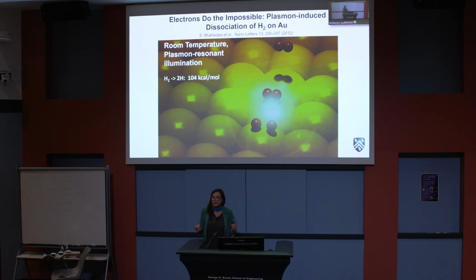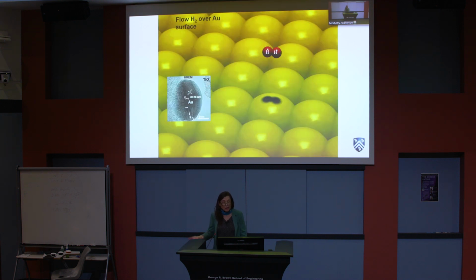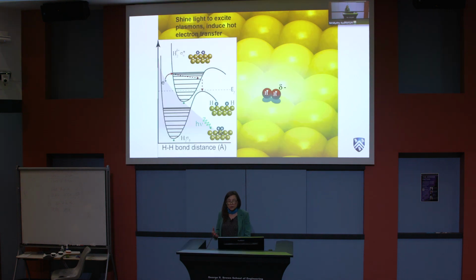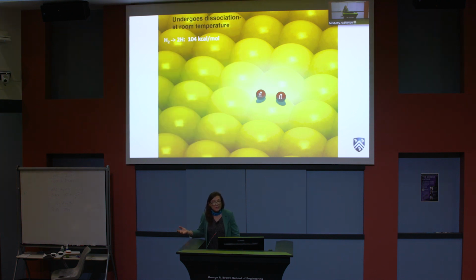So here's a little cartoon that illustrates a very, very simple reaction. What we're going to do is we're going to break apart a hydrogen molecule. It takes very, very high energy. It's a very high barrier to dissociate a hydrogen molecule. But it turns out we can do this on a gold nanoparticle surface just by shining light, transferring an electron to the H2 molecule, making it H2 minus, and put it actually in an excited state, and then dissociating this essentially at room temperature. We're not raising the temperature at all, and we're lowering the barrier by more than a factor of 2. So this is a way to get around this bottleneck of using so much thermal energy.